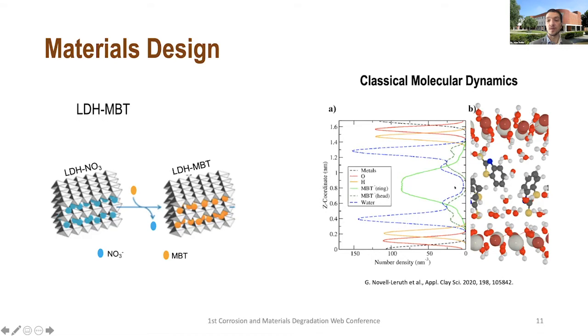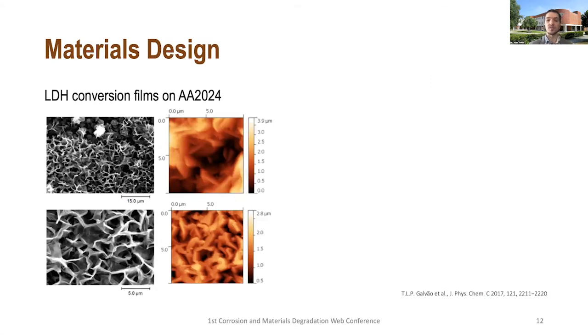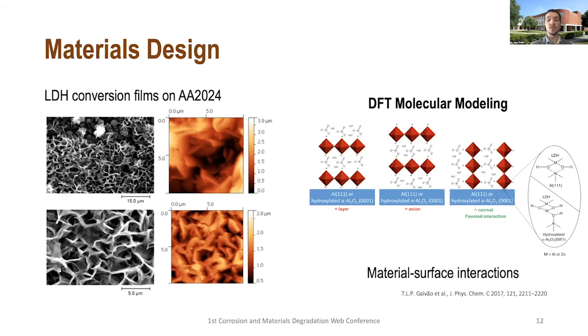So here in this example, we use classical molecular dynamics, and you can see in this snapshot of the simulation that the MBT, the 2-mercaptobenzothiazole that was being used as the inhibitor, actually is interacting with the heteroatoms with the hydroxide sheets, while the aromatic ring is pointing towards the middle of the gallery space. In addition to these kinds of interactions, we could also see that the basal spacing obtained from this simulation was compatible and consistent with experimental XRD results. So these are examples of ways in which we can use molecular dynamics to understand the position of the inhibitor within the galleries. We can also use DFT to estimate surface interaction with the material.